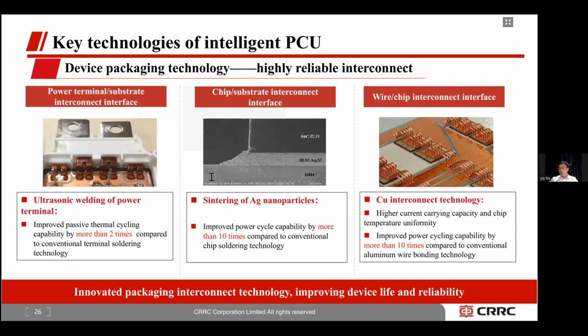And we use copper interconnecting technology by employing copper wire or ribbon bonding. The current carrying capacity and chip temperature distribution would be improved, leading to a power cycling lifetime improvement of over 10 times compared to aluminum wire bonding.